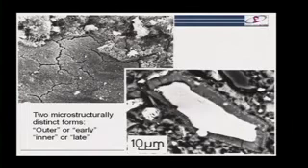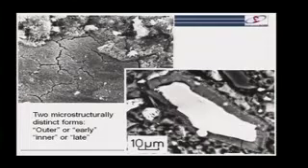Putting that aside for one moment, we then can see in the scanning electron microscope two distinct forms of CSH. I showed you earlier, we can see these quite clear rims. So this is a cement grain which has partially reacted. It's quite a big cement grain. And you see here we've got this layer of product around the grain, very, very definite, very dense and quite even. And on the outside of this layer, we've got this very, very small, sort of frizzy outside layer.